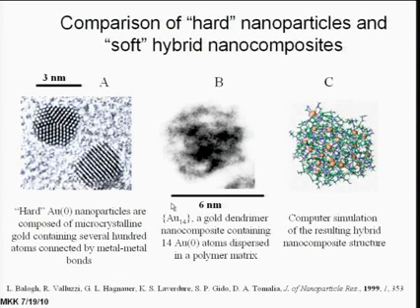This is an example of gold on a transmission electron micrograph grid. This is what we theorize a gold nanocomposite would look like, and this is what you see. You actually see these clumps of gold, and we think that's how gold gets trapped there and doesn't leach out, is it clumps together and then can't get back out again once it's clumped inside the devices. But then again, different molecules will stay in there for different reasons.